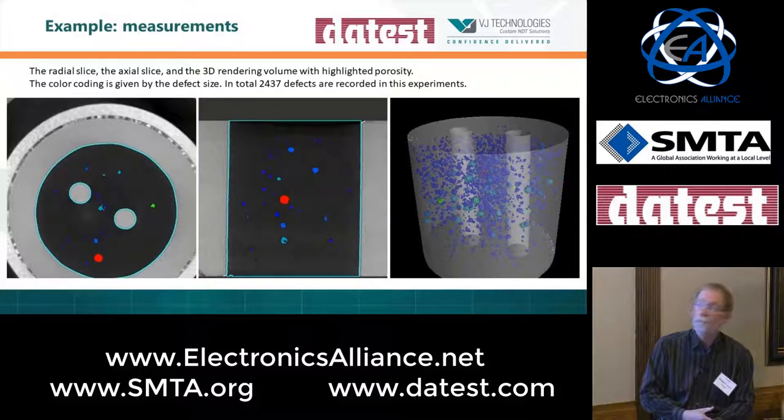This is a casting. And all the blue dots that you see looking like disease there, those are porosity measurements, which is very important in the world of casting. And software exists that can look for voids and inclusions and gaps and porosity on things like casting to ascertain what the strength of the material and the strength of the object is. Very important in reliability studies.